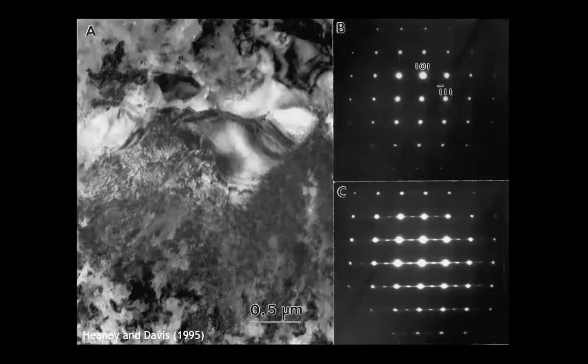They etch very rapidly in hydrofluoric acid. Those coarser crystals are resistant, and so they don't etch so quickly. And then I don't want to get too technical here, but I did some electron diffraction work on these fine-grained and coarser-grained bands. Just to show you, with the electron microscope, I can collect what's called an electron diffraction pattern. And this array of spots here corresponds to this crystal that you'll see right here.